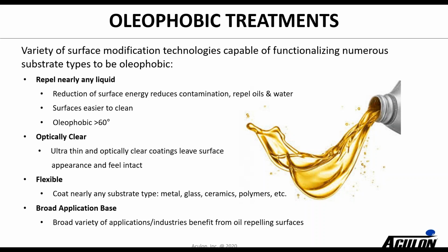And we measure oleophobicity as having an oil contact angle over 60 degrees. These treatments are optically clear, they're ultra thin, and they don't change the surface appearance, which in many cases is very important, particularly in consumer products. You're looking for the aesthetics to stay the same. They're flexible. We coat many different substrates, as you can see: metals, glass, ceramics, polymers, and we use them in a pretty broad variety of applications.